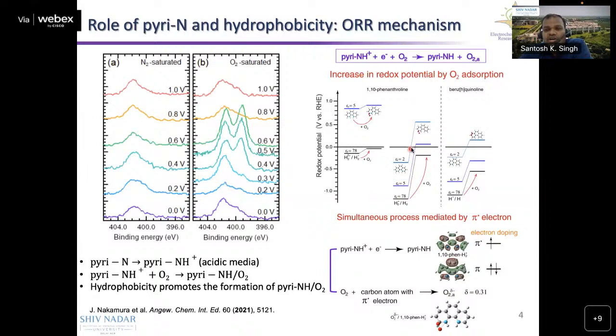So we support our result that hydrophobicity is responsible for the adsorption of oxygen, and it also triggers the conversion of pyri-NH plus to pyri-NH, because oxygen cannot be adsorbed over the pyri-NH plus, which we have seen in the XPS analysis. When the pyri-NH plus species is there, the possibility of oxygen adsorption is very low. How this is possible we can see from the DFT calculation, also from the HOMO-LUMO gap: the electron is being transferred from the oxygen to the pyri-NH plus, and it is converting back to the pyri-NH.